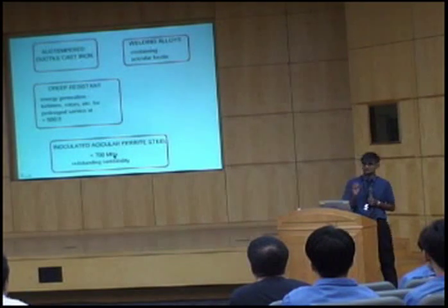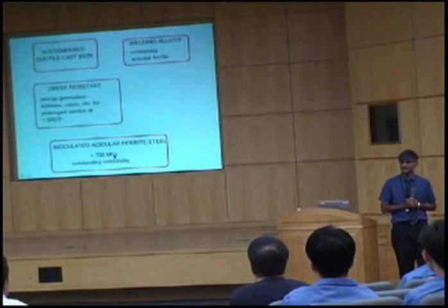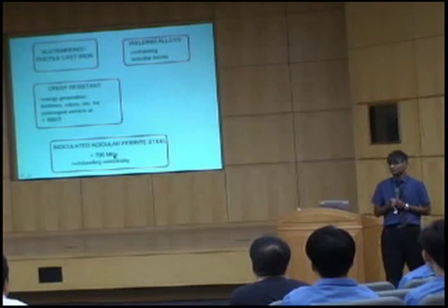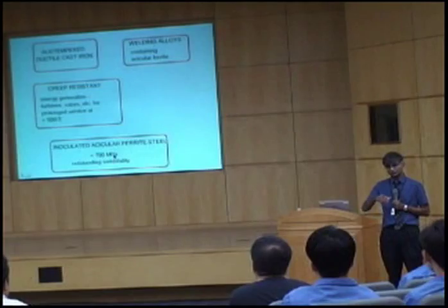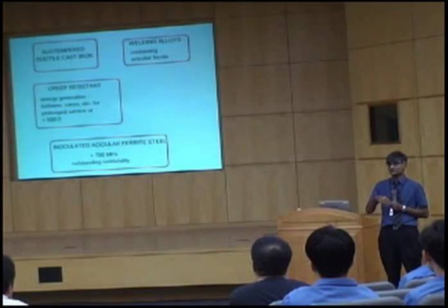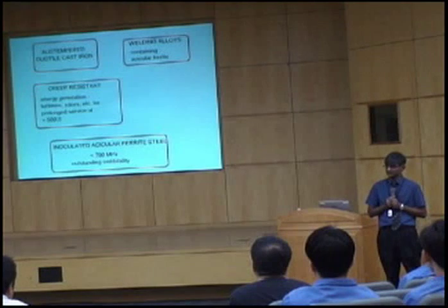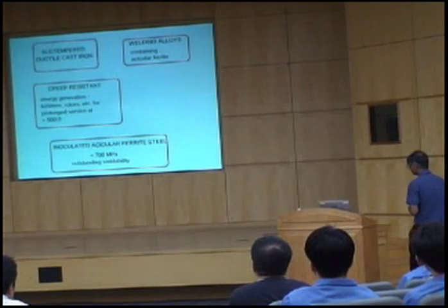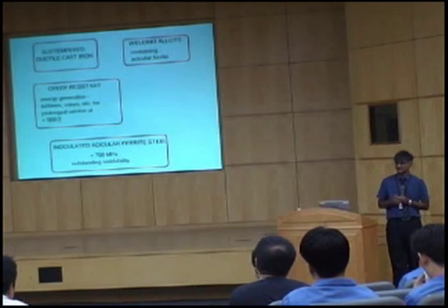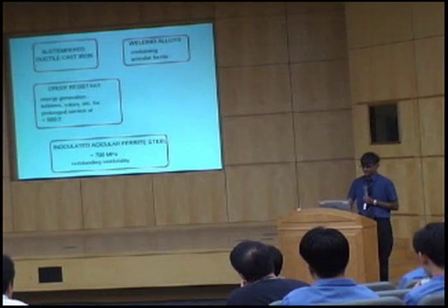And then we have this welding alloy in which you deliberately add particles to nucleate acicular ferrite on the particles and therefore produce a better toughness because the plates of bainite then point in many different directions. So the potential for bainitic steels, and already many of them are used, is huge.